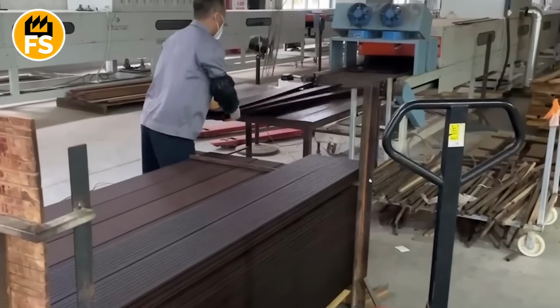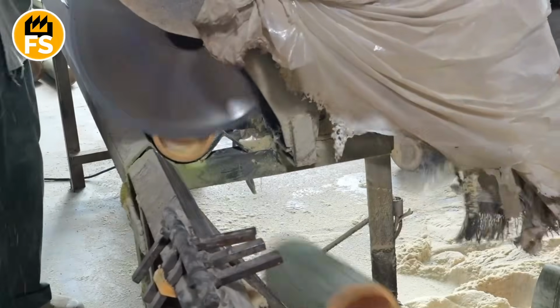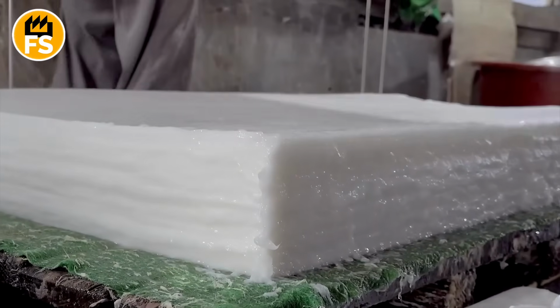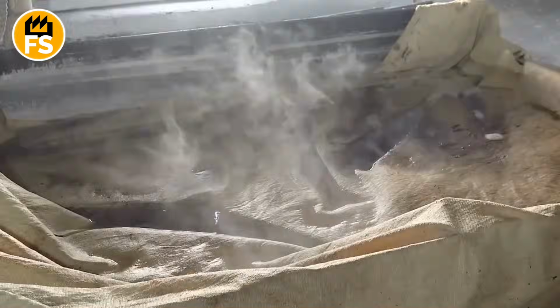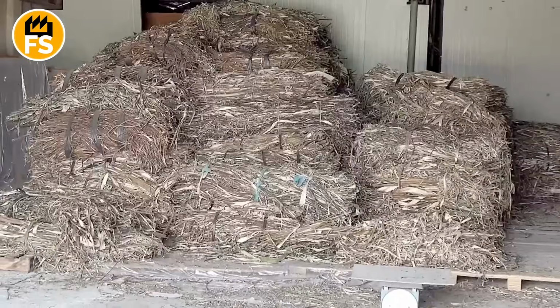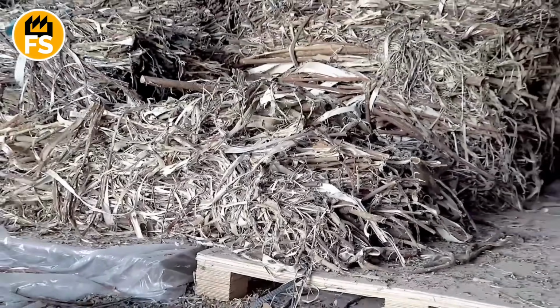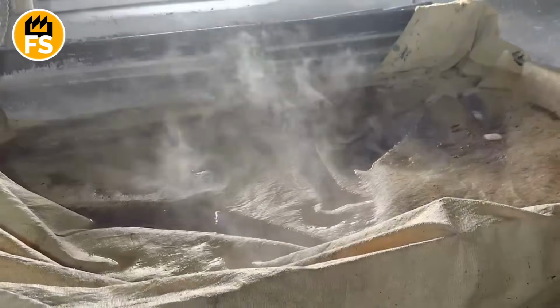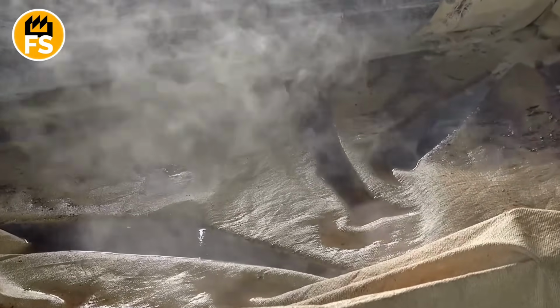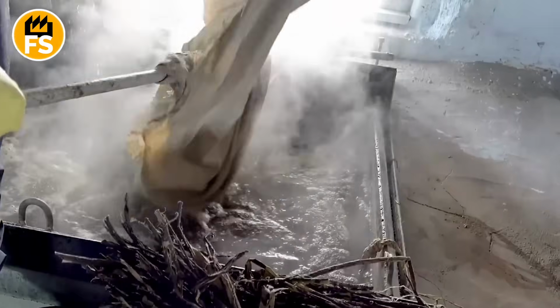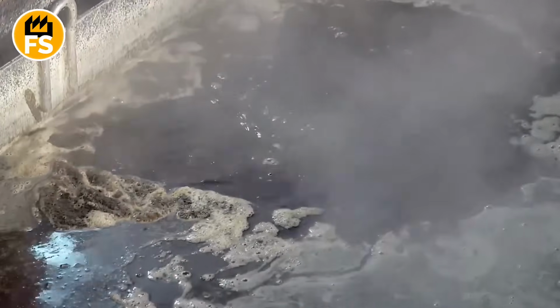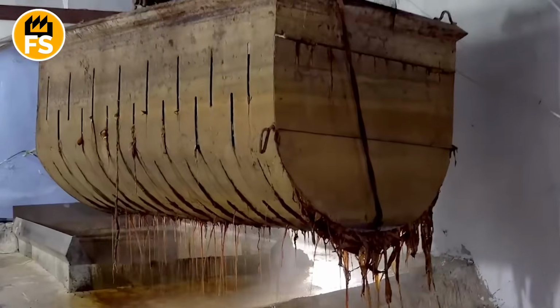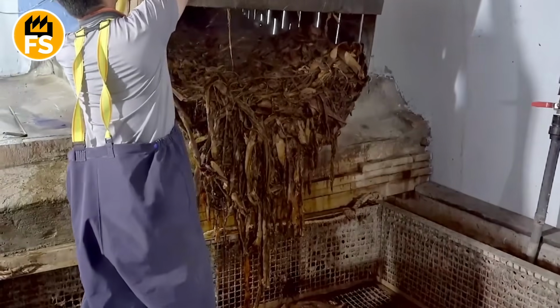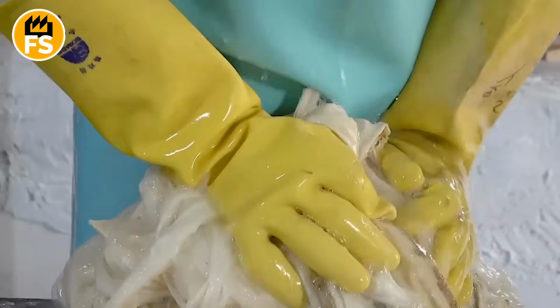The second transformation is even more astonishing. How to turn this tree-like grass into soft, silky fabric for a shirt or bed sheets. This is industrial alchemy. The bamboo culms are first chipped into small flakes. Then, the flakes are soaked in a chemical solution, usually caustic soda, that breaks down the cellulose, the plant's rigid framework. After several hours of cooking, the hard chips become a soft, thick mass that looks like paper pulp. This pulp is washed, bleached, and pressed to squeeze out excess moisture.